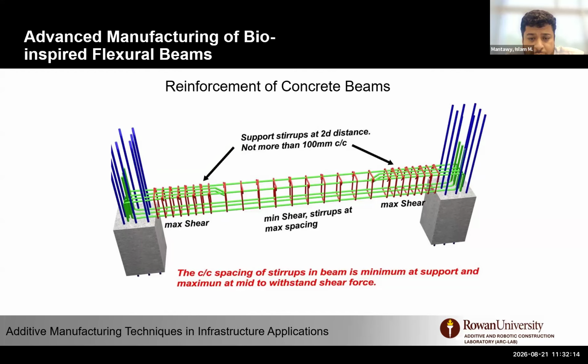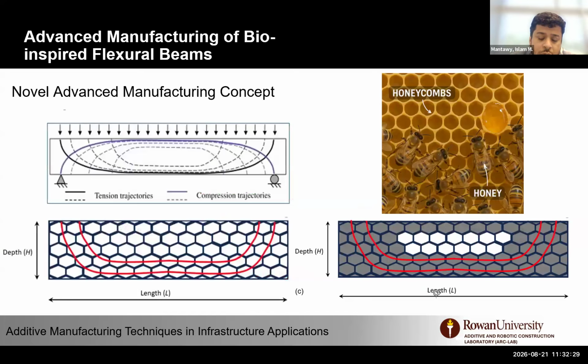So our goal here is, since our current technique is governed by the way of construction, which is formwork, can we step back a little bit and rethink the way we have the reinforcement technique for 3D printed structures? So we came up with a concept that's really from nature, from how bees build their honeycombs. So basically you will have a structural analysis of any beam, with tension trajectories and compression trajectory lines, and come up with a hybrid technique where 3D printing of those cellular units or lattice structures is able, in the process, to include reinforcement. For example, here we use flexible cable reinforcement.